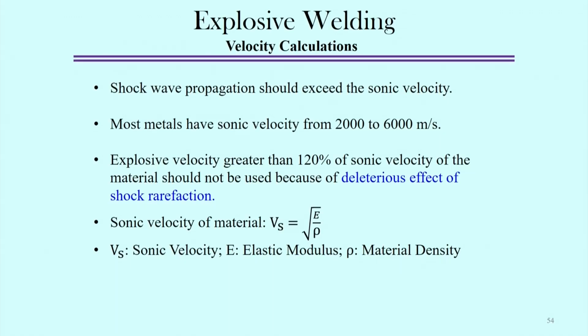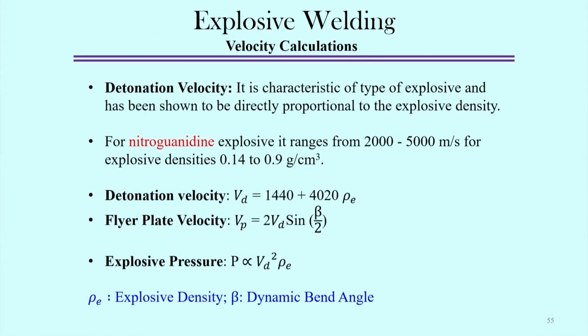because definitely the shock wave propagation velocity should exceed the sonic velocity, but it should not exceed 120% of the sonic velocity, because at this point the deleterious effect of the shock rarefaction may also happen. So, the sonic velocity of the material we can simply calculate as the square root of E by rho, where E is the elastic modulus, rho is the density of the material and V s is the sonic velocity. So, these are the typical velocity estimations that can also be done.